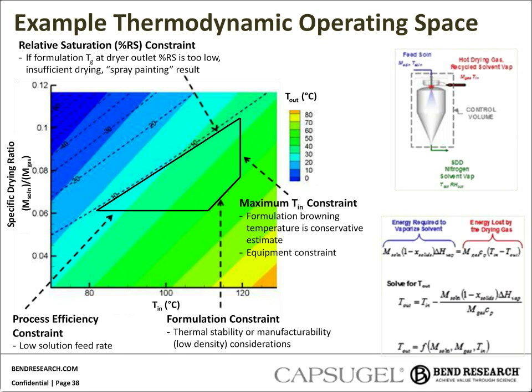You can limit the relative solvent saturation. You want to stay below a value such that the relative saturation within the dryer is low enough to prevent sticking, and this can be assessed by evaluating the Tg of the SDD at various solvent saturations. In order to achieve an efficient process, there's likely a minimum spray solution feed rate that you can define. And last, you can define a maximum or target outlet temperature based upon SDD product attributes or thermal stability. We'll talk more about that aspect, correlating the outlet temperature to the SDD attributes, in the next slide.